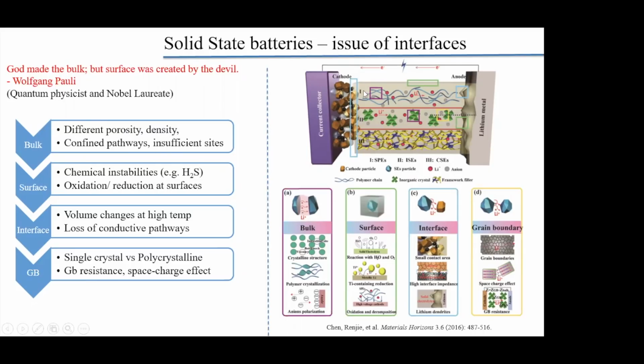If it is all concentrated in one point or another, then it can lead to imbalance, and that could be a failure point. It has to be uniform, going back and forth, and the whole interface has to have the right kind of porosity and density of materials. Pathways should exist along the whole surface. So that's at the bulk level.